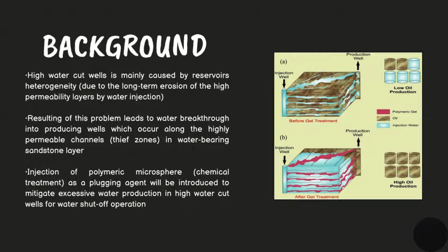Now, I will briefly showcase the background of study in my project. High water cut wells are mainly caused by reservoir heterogeneity, which is due to the long-term erosion of the high permeability layers by water injection. This problem leads to water breakthrough into producing wells, which occurs along the highly permeable channels, called thief zones, in water-bearing sandstone layers. Thus, injection of polymeric microsphere, a chemical treatment acting as a plugging agent, will be introduced to mitigate excessive water production in high water cut wells for water shut-off operation.